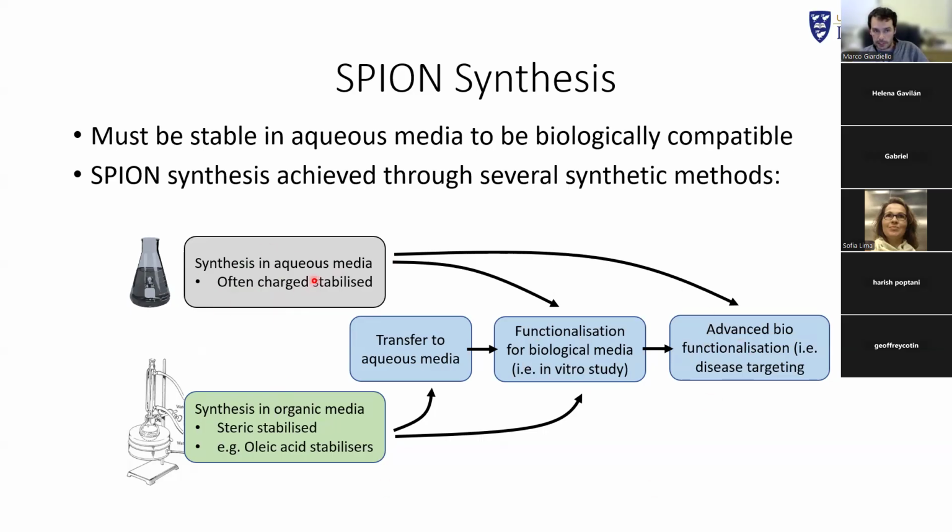So you have to consider putting them in something afterwards for your biological application. It's less of an issue when it comes to co-precipitation, and that's the reason why co-precipitation is so popularly used. All of those previous ones, apart from maybe the MPIO, were made using co-precipitation. Thermal decomposition gives you very controlled, very crystalline particles that are absolutely brilliant. But the problem is they're quite often in toxic organic solvents. So you will always have to do this step of transferring them to aqueous media, and that can be a problem. Not only do you have to transfer them, but you have to ensure that any of those toxic stabilizers all disappear. Then you'll have to functionalize them. Then you have to try and do your advanced stuff with them as well.